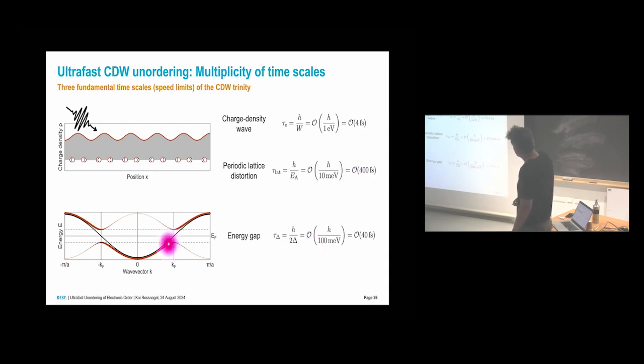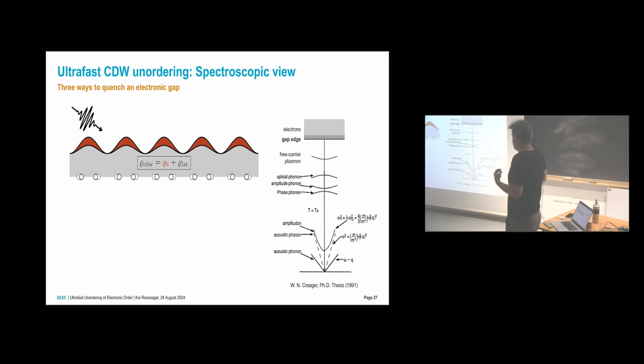And then if you think of the gap, what's the energy scale of the gap? The energy scale is 2 delta, and this transforms into a typical time scale. If you take 100 millielectronvolt as a typical charge density wave gap, then this gives you 40 femtoseconds. And you already see that there are a number of different time scales, and this gives rise to a multiplicity of processes, and so this can be complicated. And so ultimately, we of course want to be really, really fast and then look more into these electronic time scales. Okay, and then how can we look at this from a spectroscopic point of view?